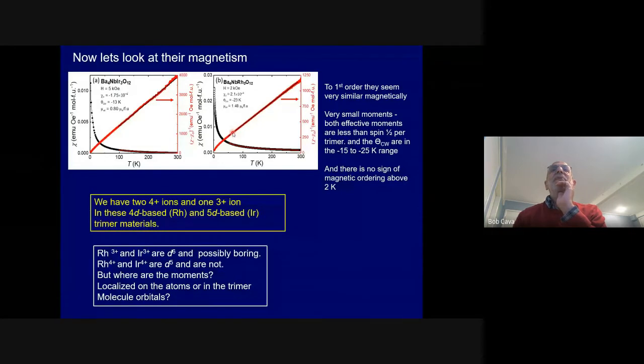But this rhodium compound has this kind of Curie-Weiss susceptibility, which can be fit by the Curie-Weiss law up here at high temperature, where you're supposed to fit it, and it doesn't magnetically order down to 1.8 Kelvin, which is the lowest temperature we can measure with this technique. Same thing for the iridium. I know that iridium can be magnetic a lot of times, so that's all good.